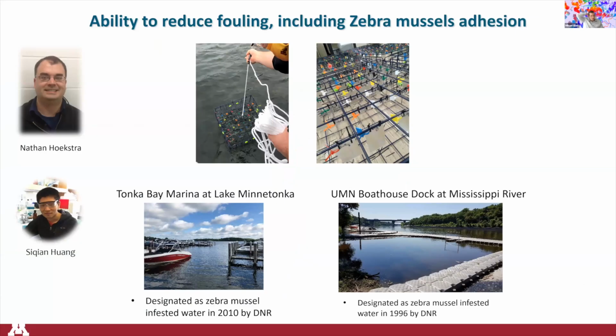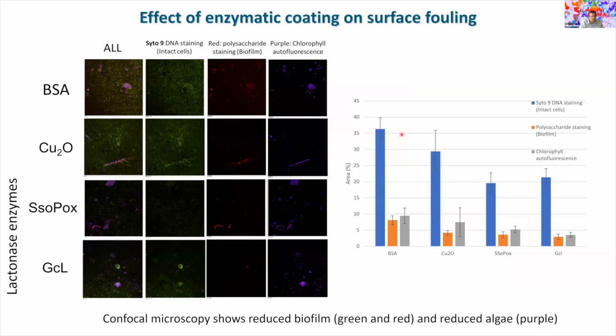Now, looking at fouling in more detail, shifting now to some of the work of Siqian and Nathan, where they've done field experiments in Minnetonka and on the Mississippi River. This is some experimental setup that they've used, some cages with suspended coupons of different material. This is probably polycarbonate here that was coated. During these experiments, we can look at a bunch of different parameters that were similar to those examined in the Duluth experiment. This was an experiment that was performed, I believe, in the Tonka Bay Marina at Lake Minnetonka.